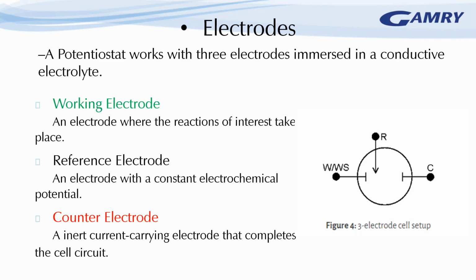So the potentiostat works with 3 electrodes, usually immersed in some conductive electrolyte. The working electrode or sample electrode is the place where the reactions of interest take place, either close to the electrode in solution or from the electrode itself. The reference electrode is the electrode with the constant electrochemical potential, where we reference all the potentials that we measure against the reference electrode. And the counter electrode is an inert current carrying electrode that completes the cell circuit.